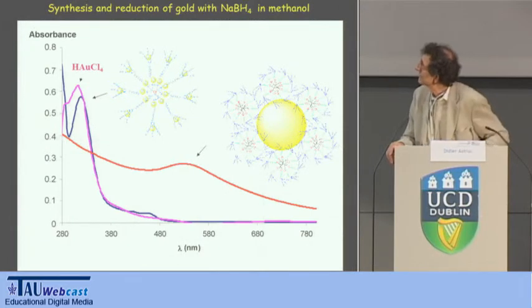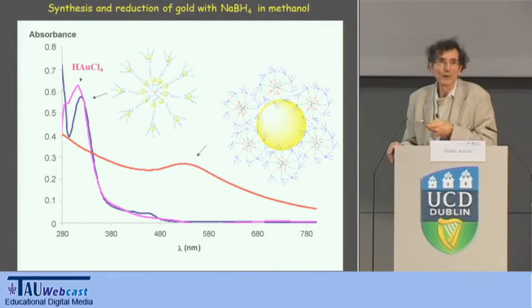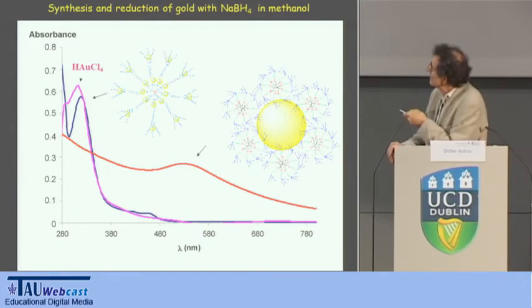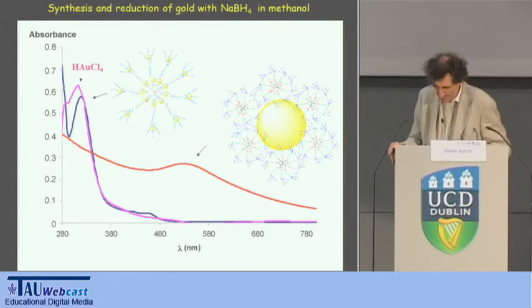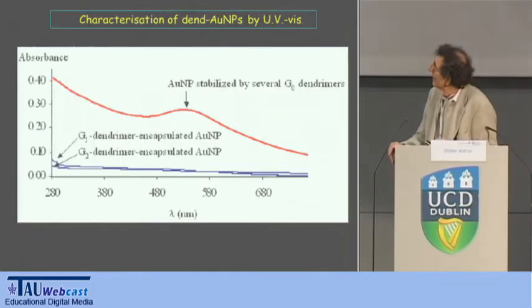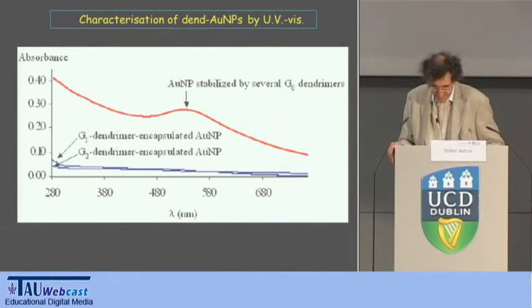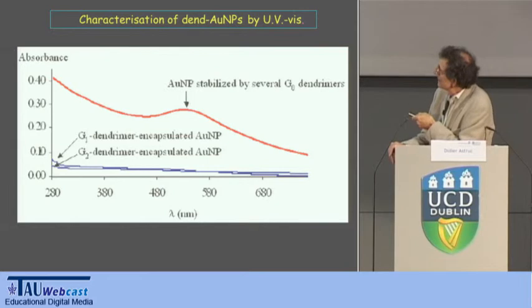So here you see what happens if you reduce gold tetrachloroauric acid, and you have a purple line for the gold(I). If you coordinate the ligands in the dendrimer with gold(I), then you have a UV-visible band which is almost the same. So the blue here is almost the same as the purple. It's still gold(I). When you reduce to gold zero, then the gold zero has the visible plasmon band. Here you can characterize the nanoparticle in this way. So the dendrimers can allow you to generate the nanoparticle.